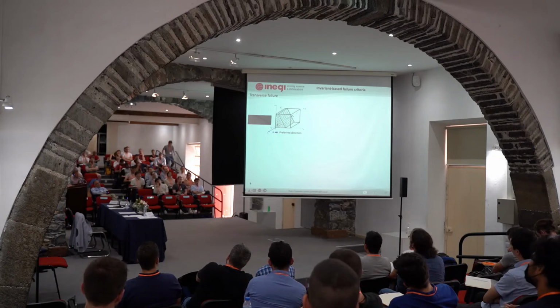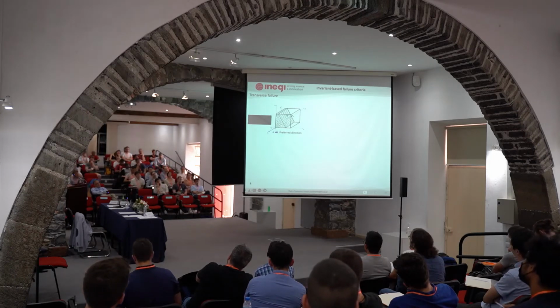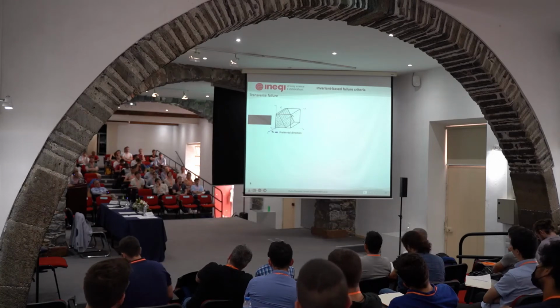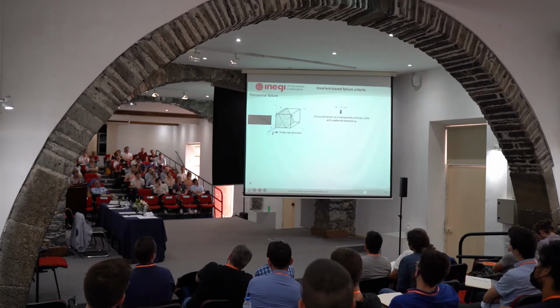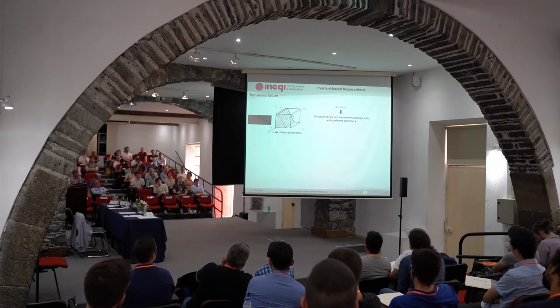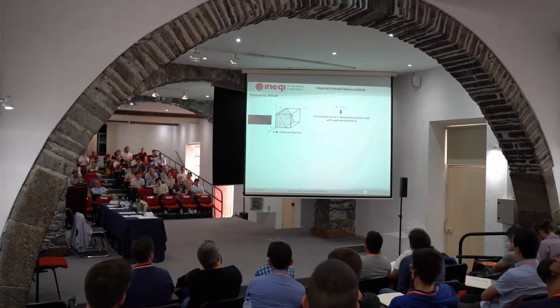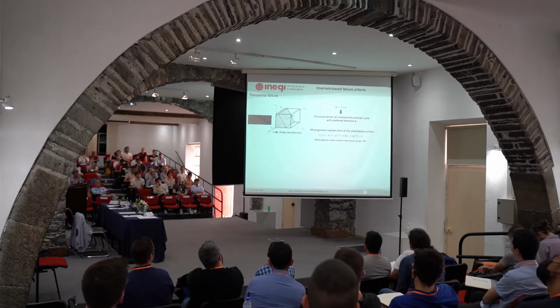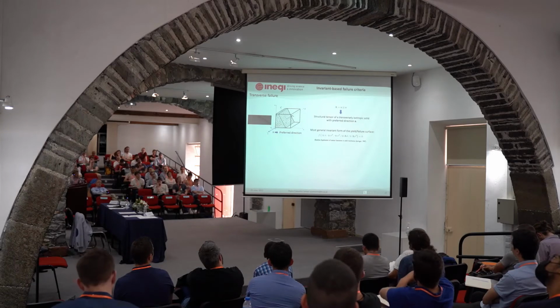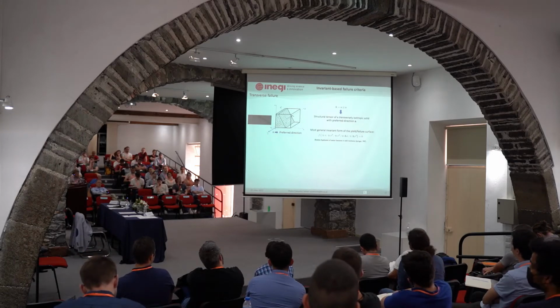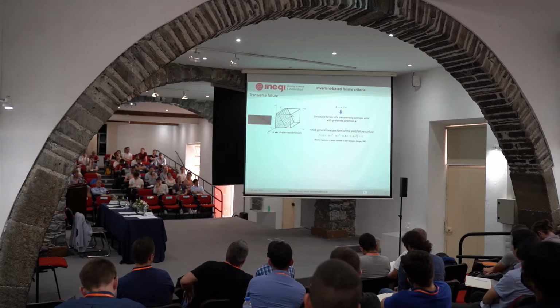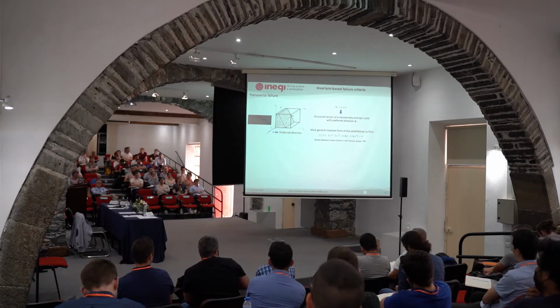And we take a composite laminate as a transversely isotropic solid with a preferred direction, which is the fiber direction, that is defined by this unit vector A, okay? And with that, we can form a structural tensor of a transversely isotropic solid with this preferred direction, okay? Now, back in the 80s, Jean-Paul Boehler demonstrated that the most invariant form of yield or failure surface can be established in terms of the invariants of the stress tensor and of functions that use this structural tensor and the stress tensor as well.